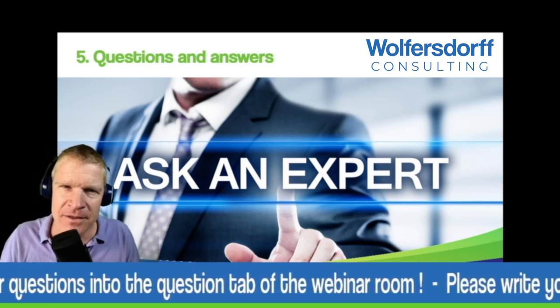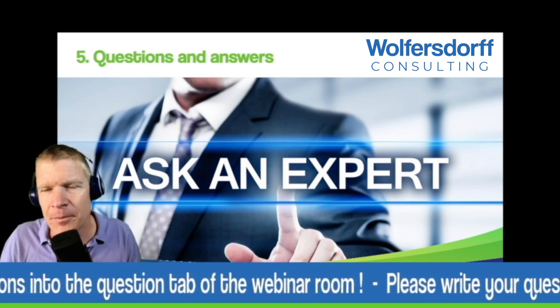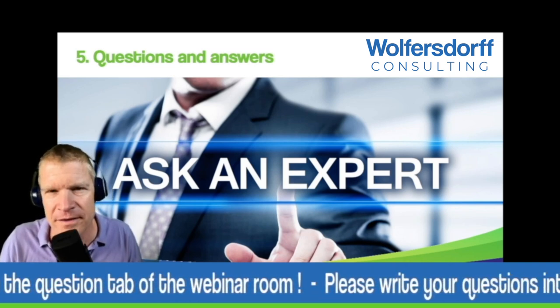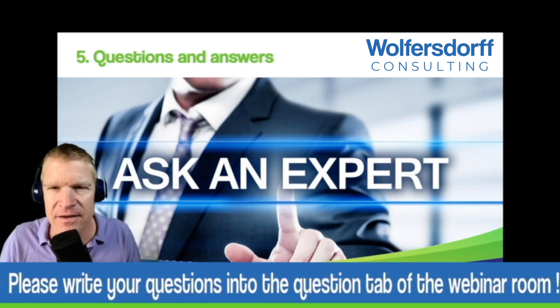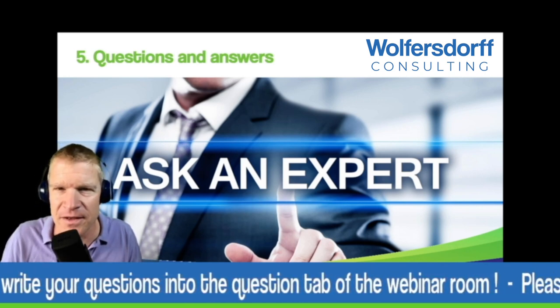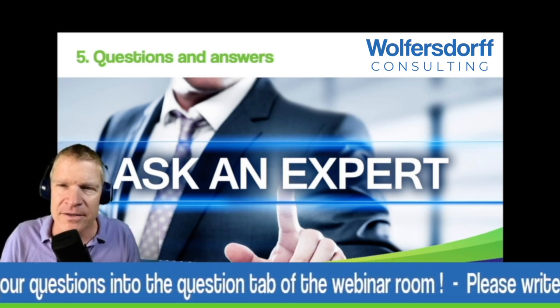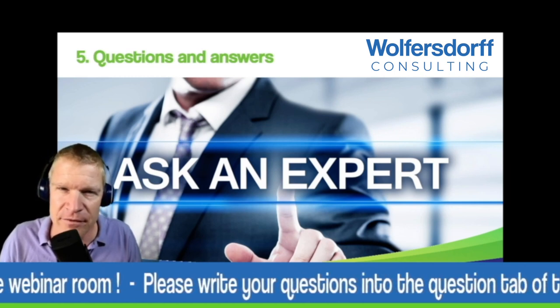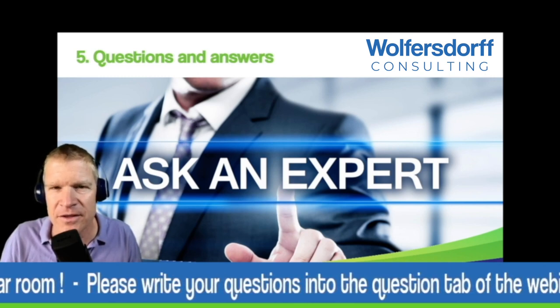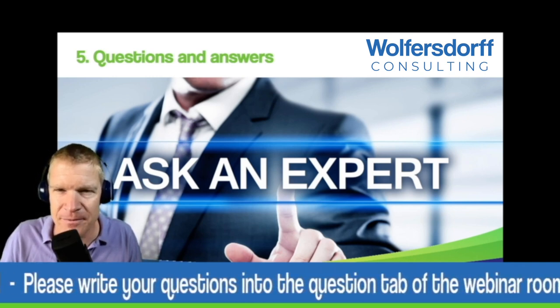Ravi from Capital Carbon asks, Martin, for pelletization, what is the best binder for plastic uses? The binders used in carbon black tend to be molasses, so sugars, waste from the sugar industry, or lignosulfonates added at a low concentration, I think below 1%. I don't remember the exact percentage. I have heard of recovered carbon blacks that didn't need any binder for making pellets, that have really nice pellets and also pellet hardness without any binder. So I would say it depends, but the starting point would be molasses and lignosulfonates.